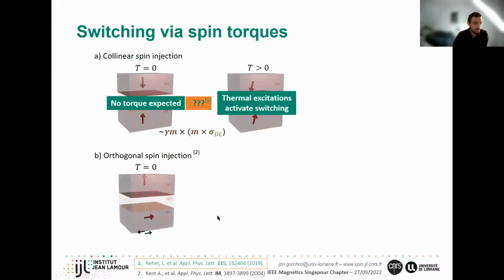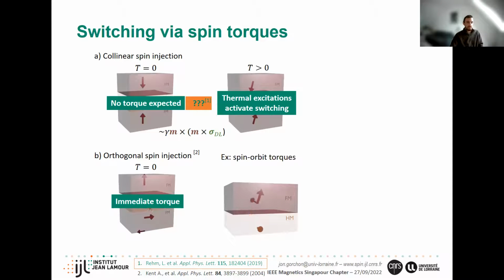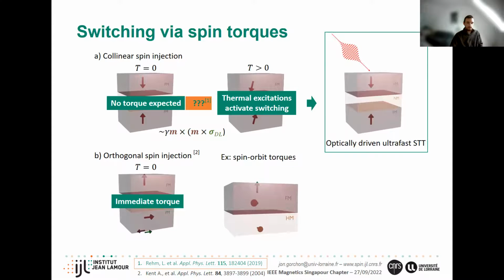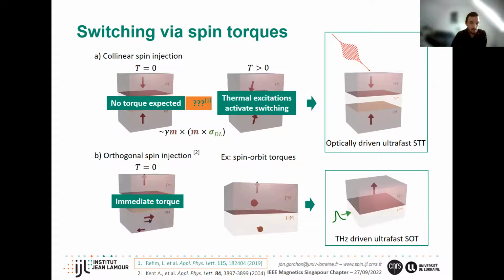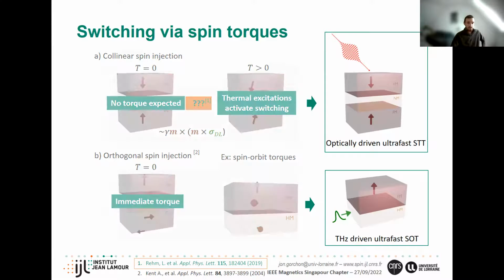And so here, when you inject the spin current, you get an immediate torque, whether you have temperature or not. And so this is exactly the configuration that you get when you do the spin Hall effect, or when you try to do spin orbit torques. The torque is immediate. So in the following 15 or 20 minutes, I'm going to talk to you about 2 methods that will exploit either the collinear configuration, where we're going to use light to generate the spin currents, or the transverse configuration, where we use a terahertz pulse to drive spin orbit torques at ultra-fast timescales.